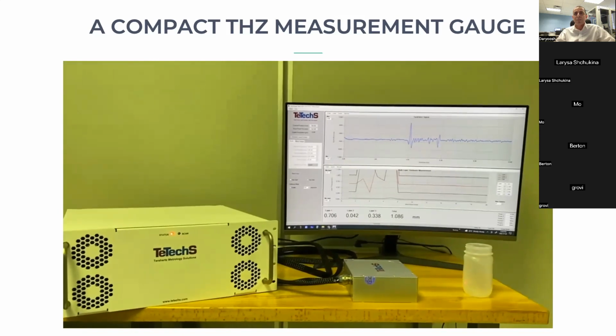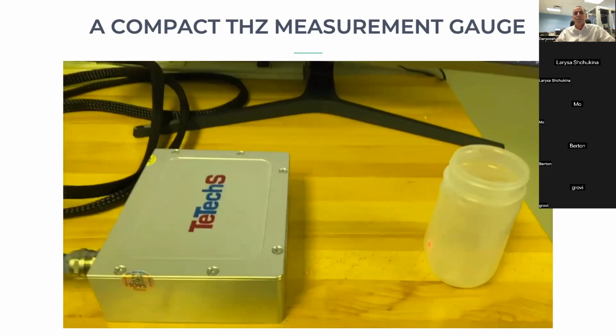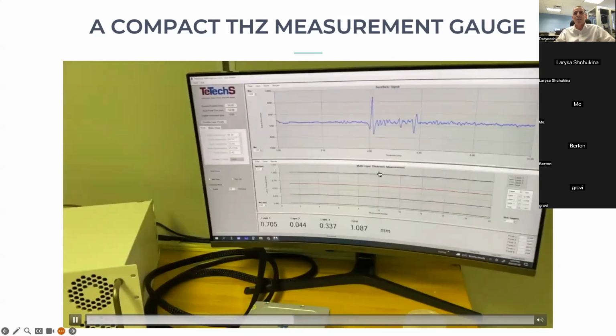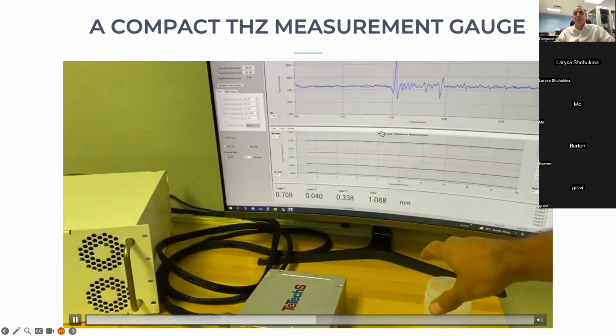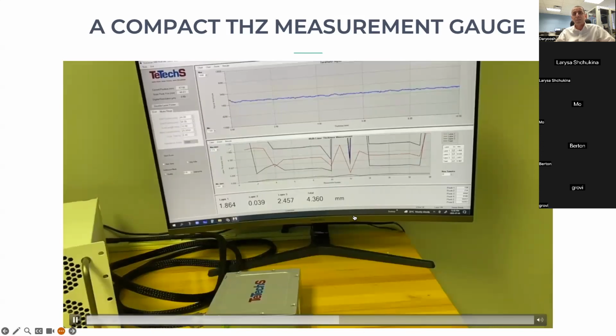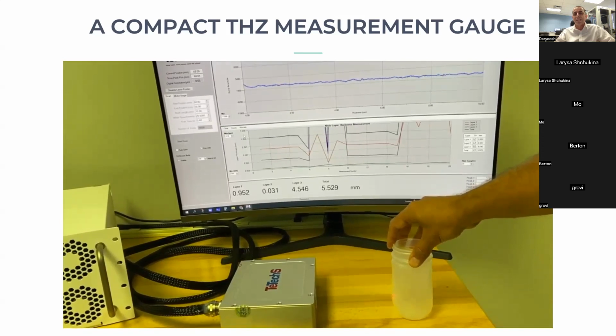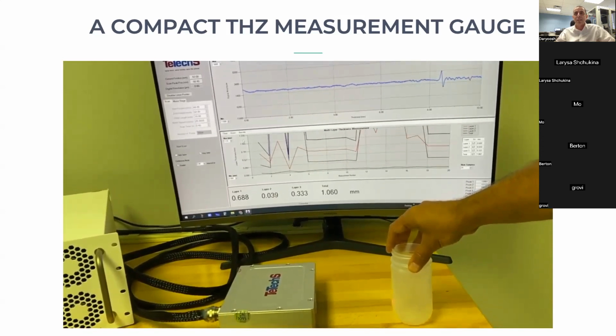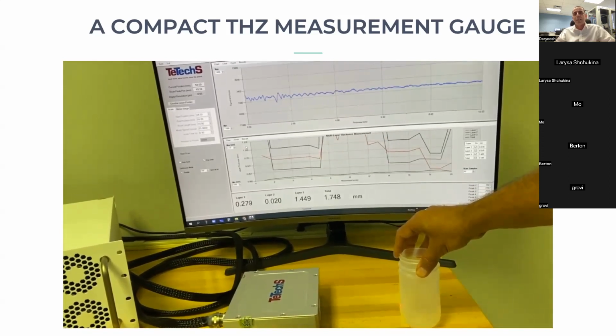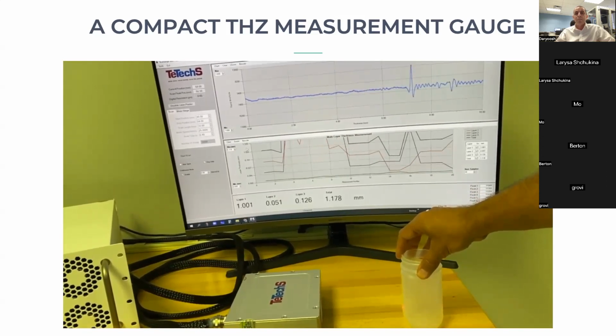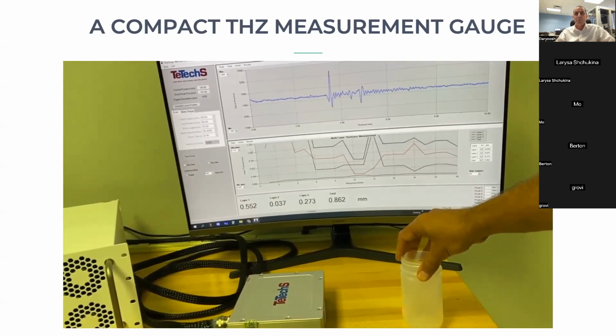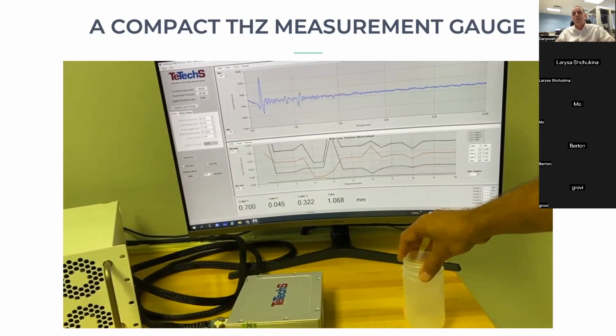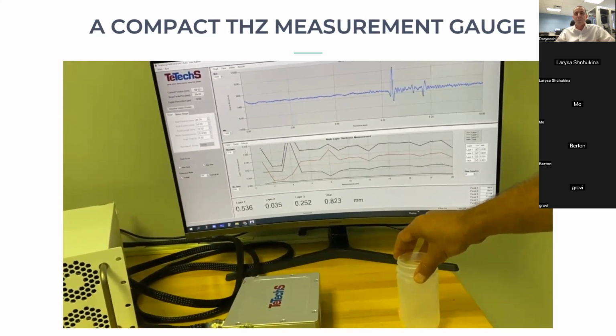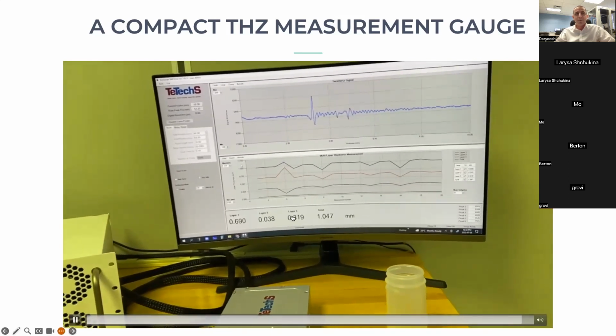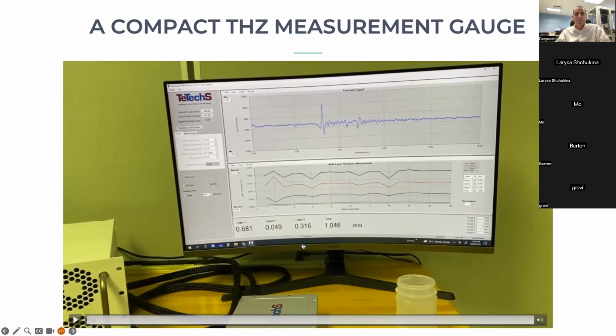So that layer, as well as the wall thickness, gets measured here almost in real time, as you can see. And the echoes from each layer, the front surface, the barrier, as well as the other side, get recorded. So what this video is trying to show is how forgiving the positioning of the sample in front of the sensor can be in this kind of measurement, versus, for example, some of those laser-based or visible light or IR-based measurement techniques. You have to position the sample with micron precision in front of the sensor in order to get a reading. Here, it is a lot more forgiving. It can be a few millimeters back and forth, and you still get a reading. So a system like this has the potential to get into a factory floor, and we have actually put a bunch of those in the manufacturing space, and it's running really well.